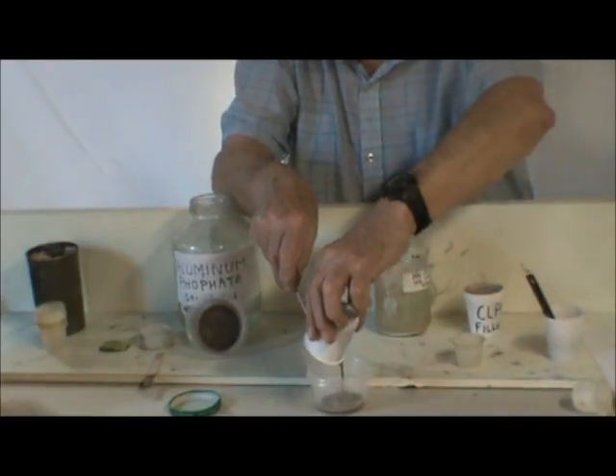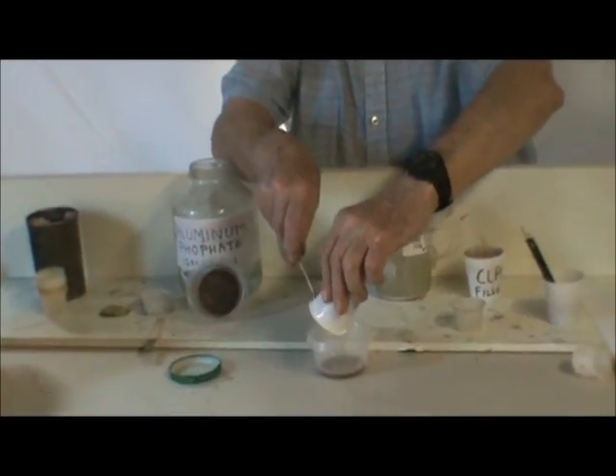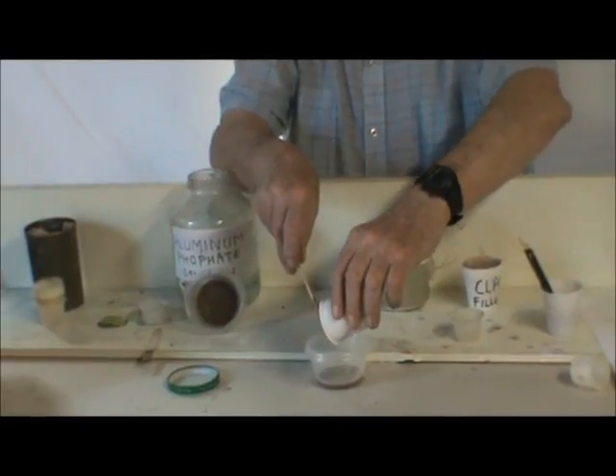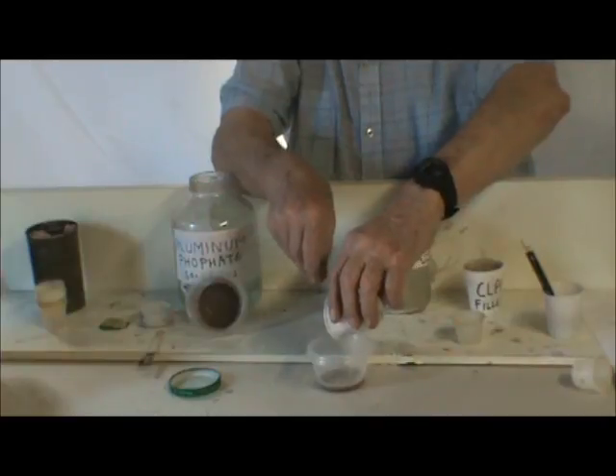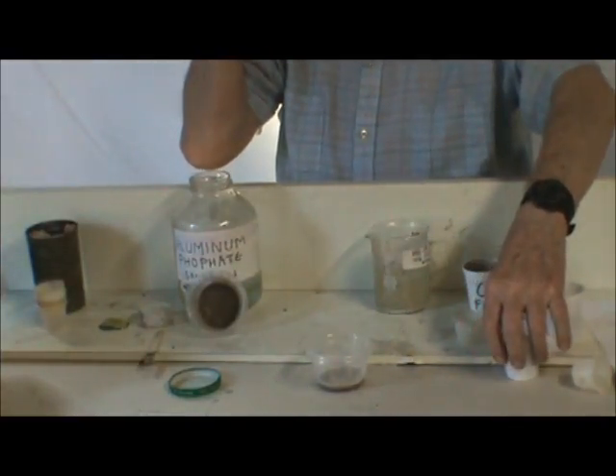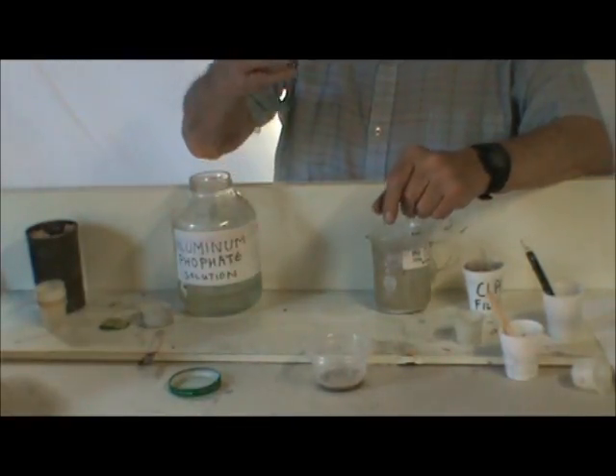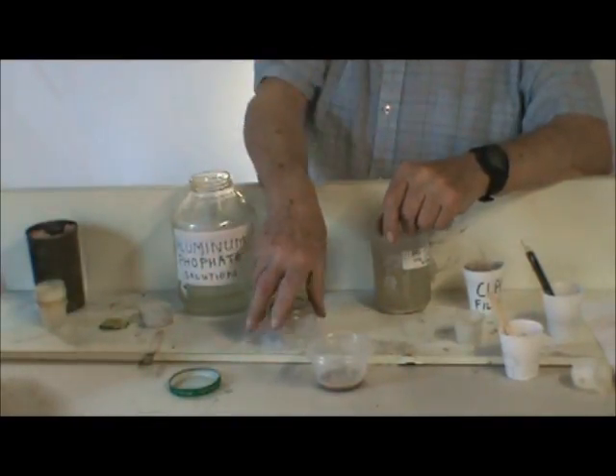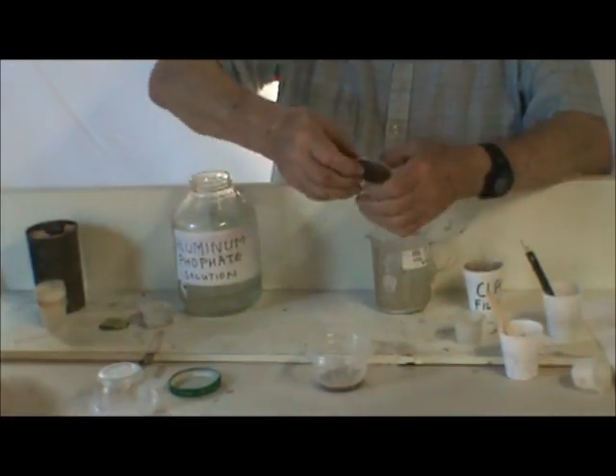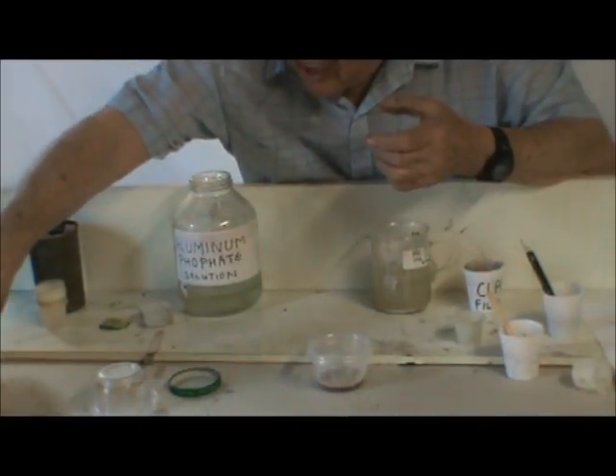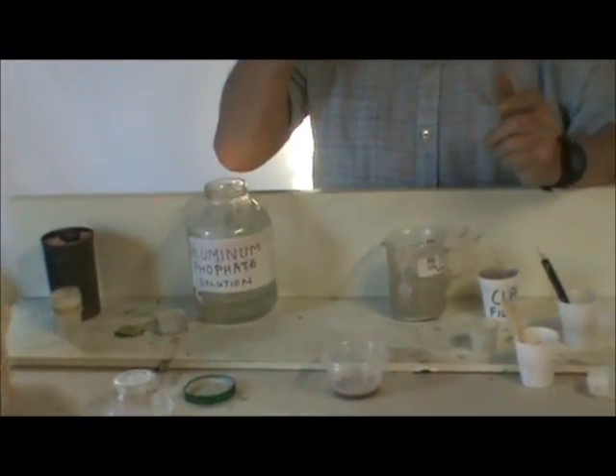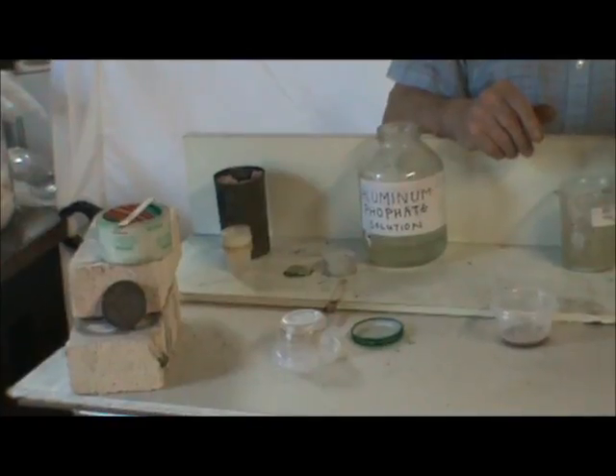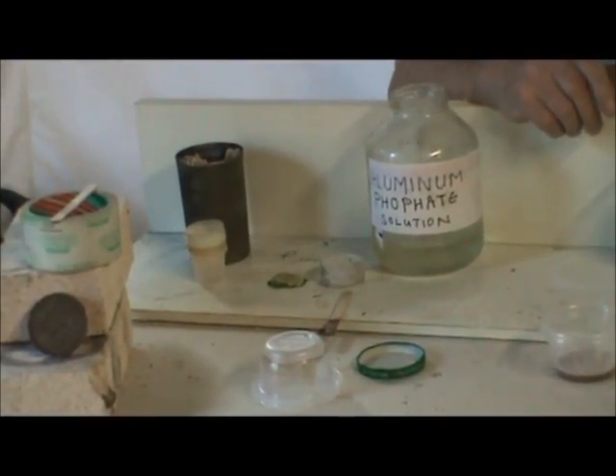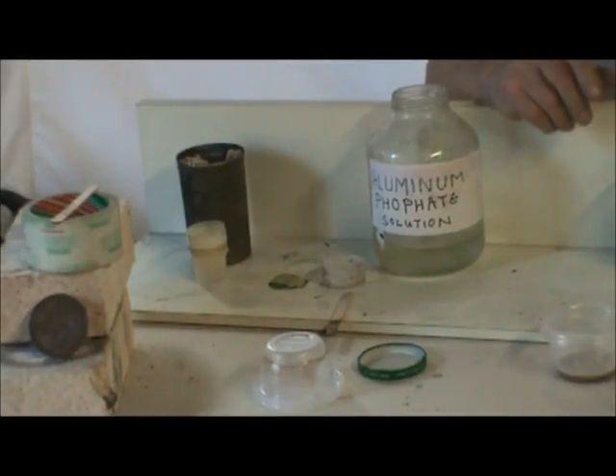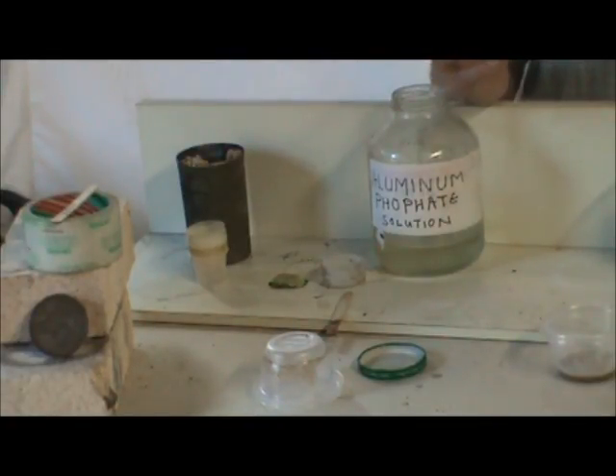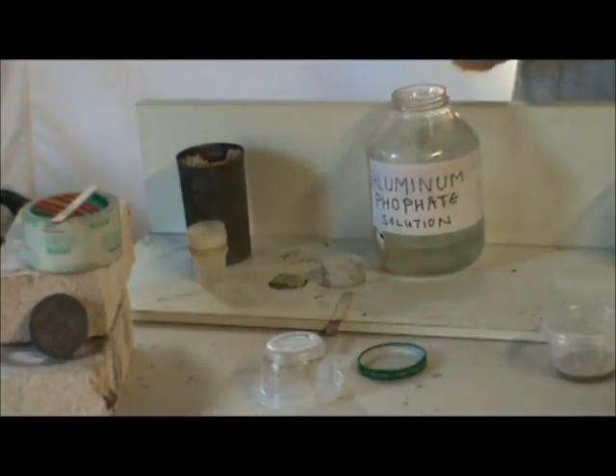I'm going to pour it now, and while that is solidifying, I'm going to demonstrate the other remarkable property of this magnesium aluminum phosphate mix. I'm going to show that we can take this solidified sample that we just poured and hit it with a very high temperature flame. As you can see, we have a solid cement-like sample, and now we're going to hit it with an oxyacetylene flame, showing that it has amazing resistance to falling apart when very high temperature heat in excess of 4,000 is applied. You have to put it on pause now while I light the torch.